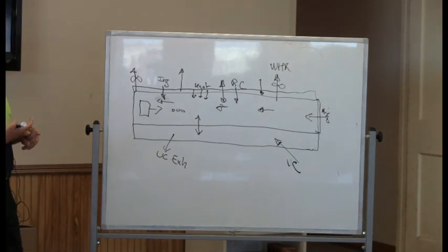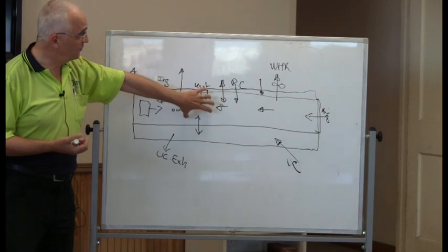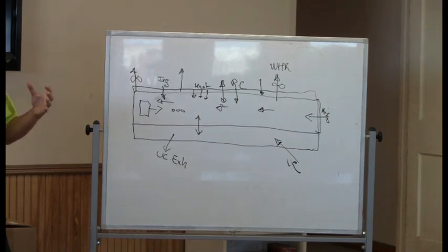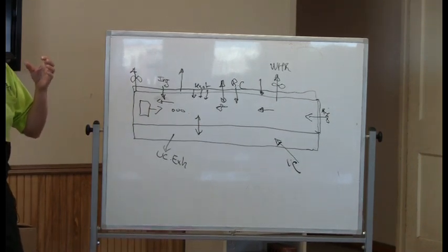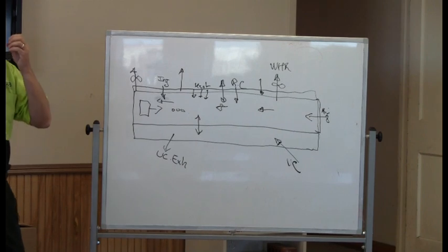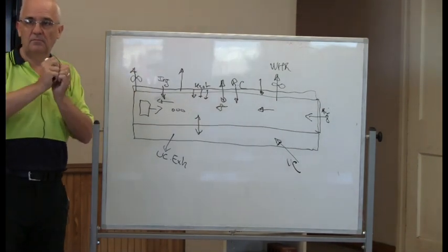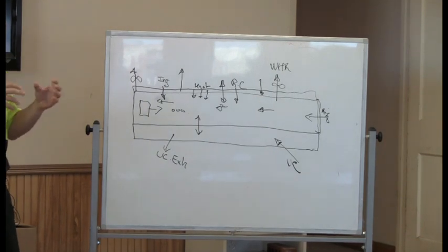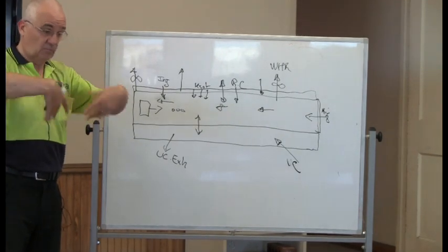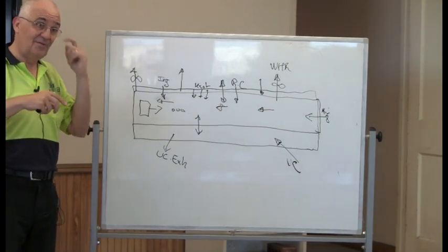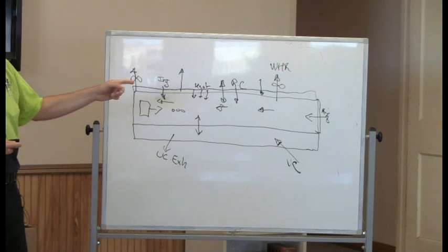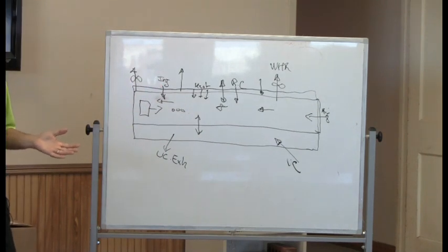Also, when you don't have enough air in the tunnel, your flame is more prone to flame impingement, that's the right term? Hot spots. Because you don't have anything to actually distribute that heat. And if you allow the heat to be trapped in the firing lane without going away, you don't heat just the firing lane, you want to heat the whole load, then the air has a crucial role to play.